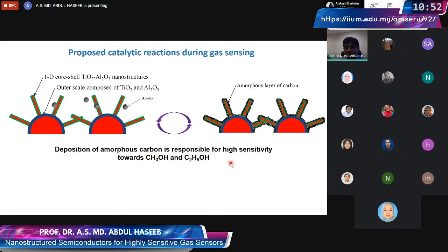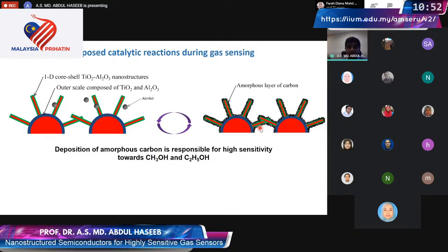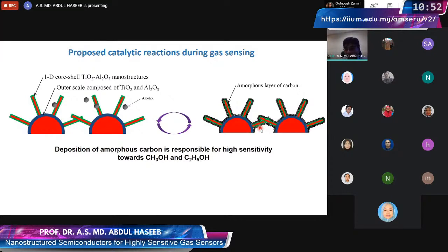So we propose this is what is happening. When we expose our material to this environment containing alcohols, as a result of interaction with this, we have a deposit of this amorphous carbon. As a result, the resistance decreases tremendously and we get a very high response, which we cannot get with other gases like hydrogen sulfide, because the mechanism is different. Now, this leads us to dig a little bit in detail into the literature, particularly our colleagues in catalysis. They have done a lot of work in the past on the interaction of these chemicals with oxides, of course from the catalyst's point of view.